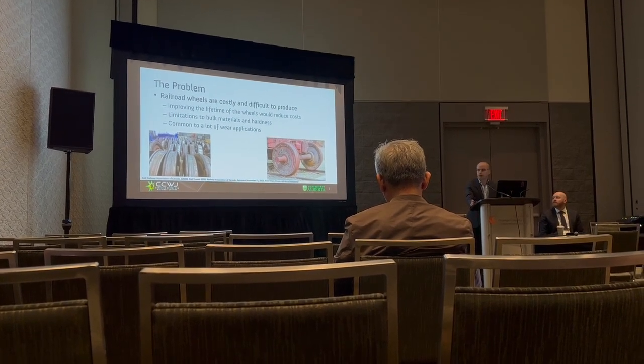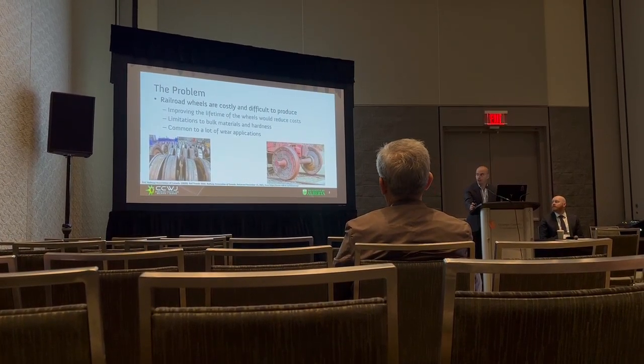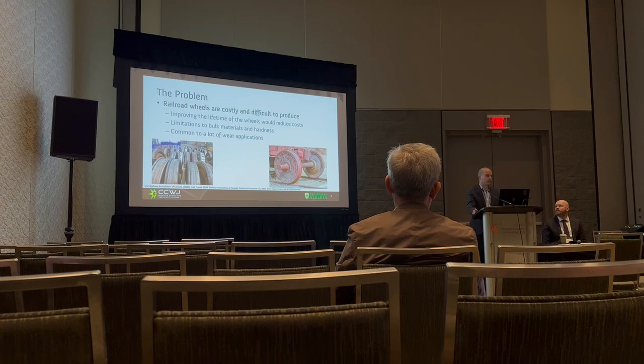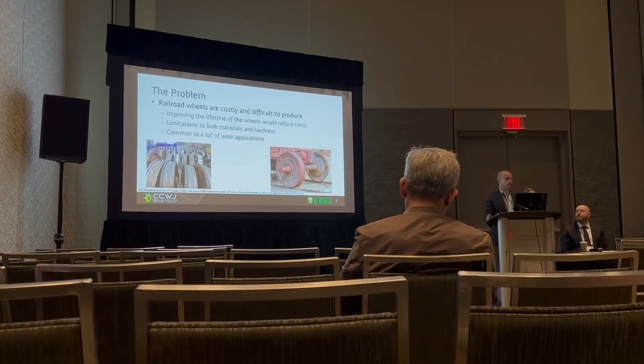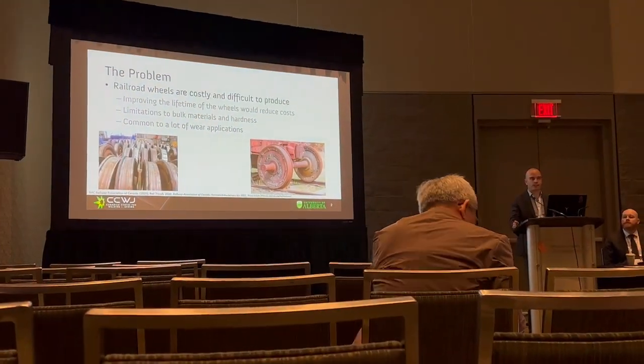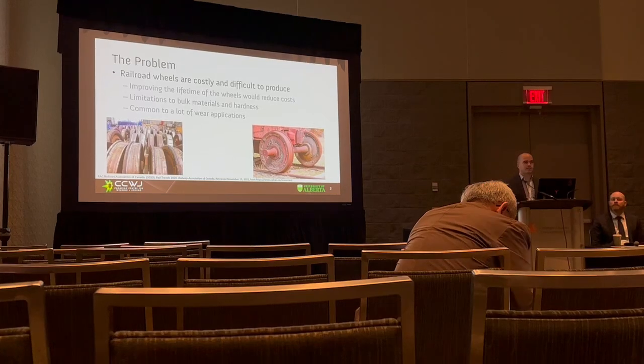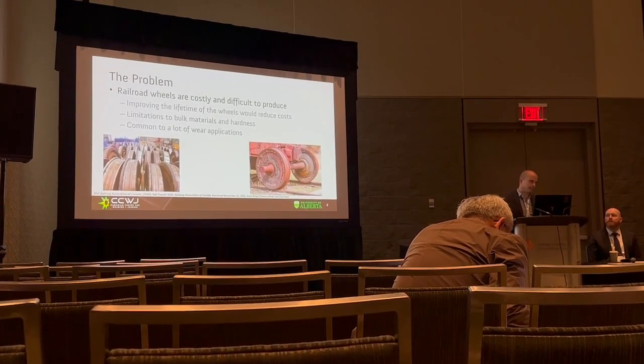So there's actually only, depending on the wheel and the surface, a little over an inch of functional material that will actually see a track in the whole lifetime of the wheel. And the whole rest of that half ton of steel is then scrapped and remelted.